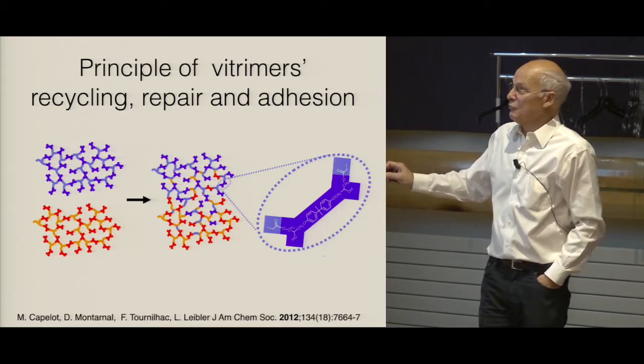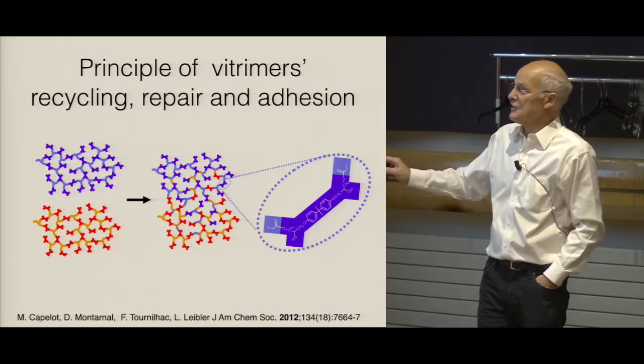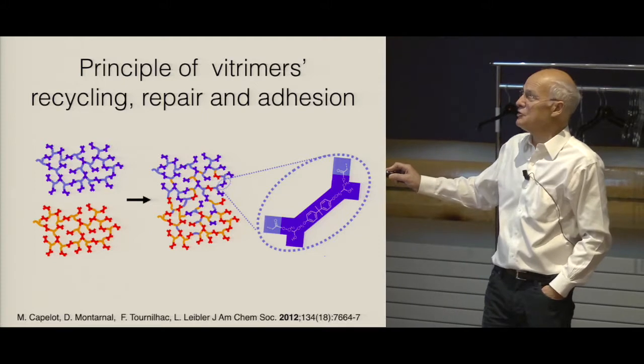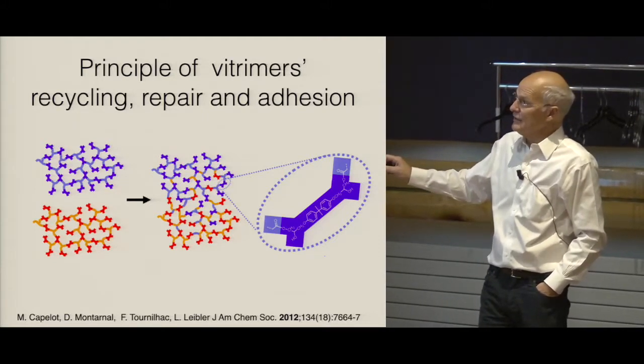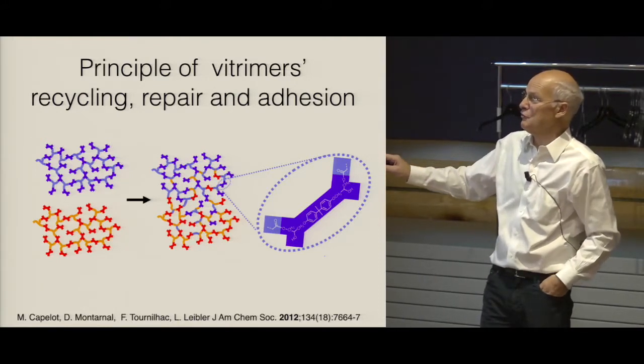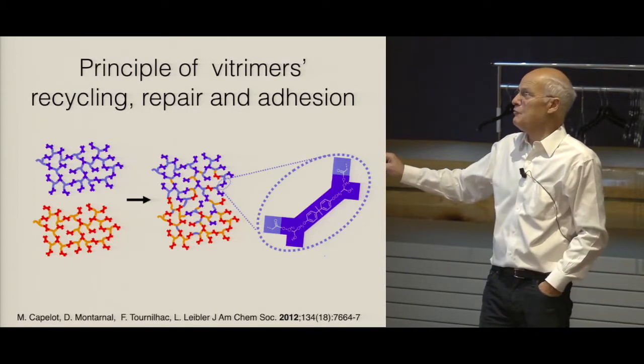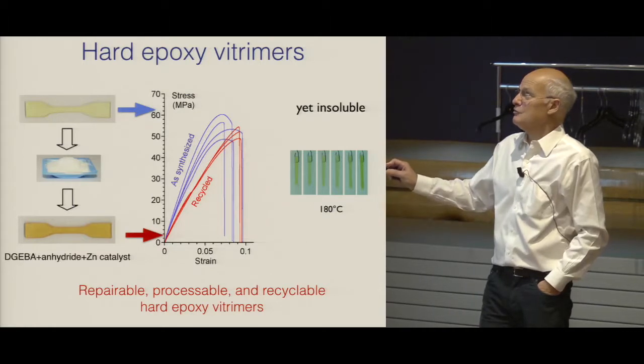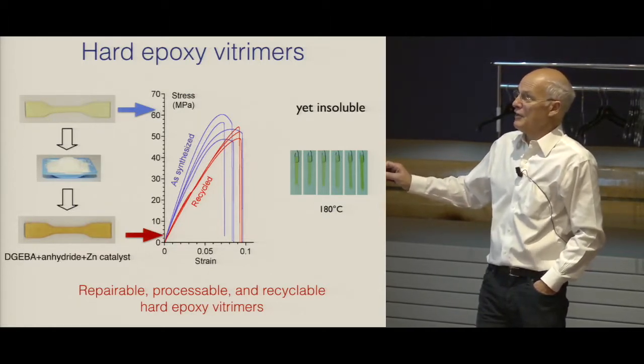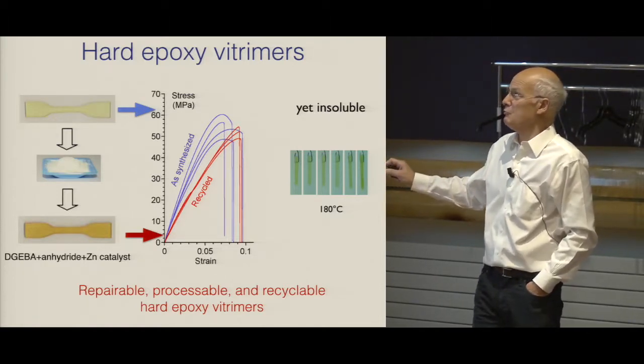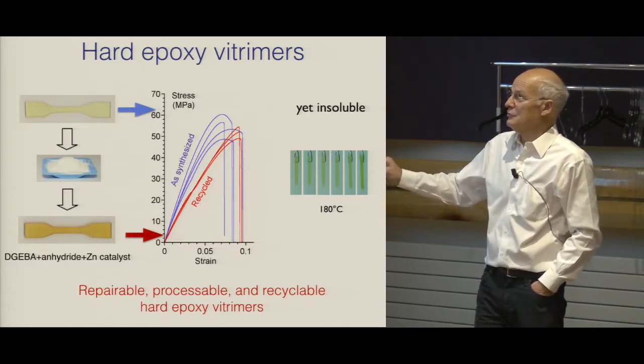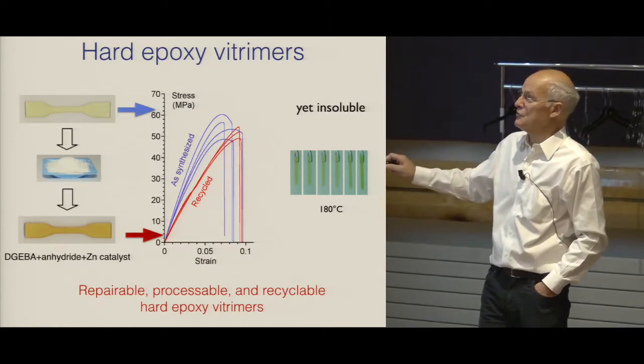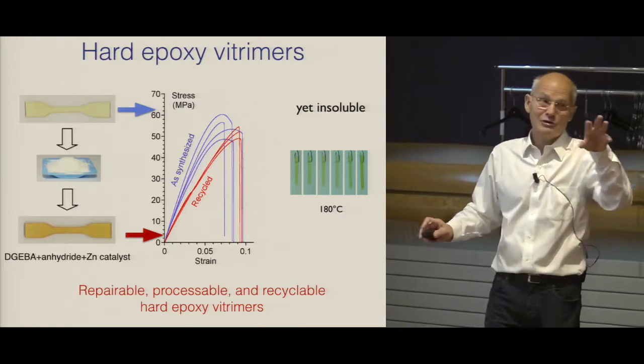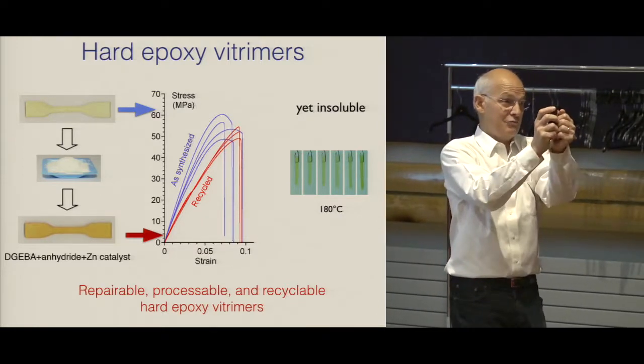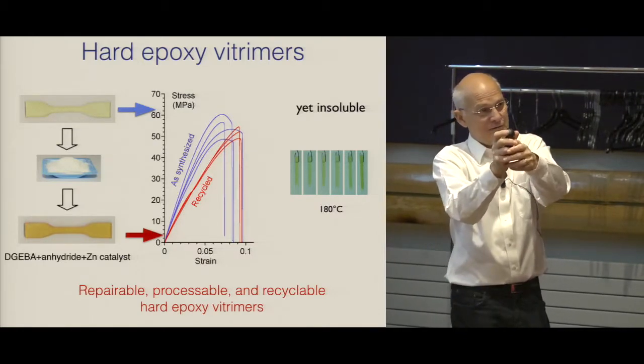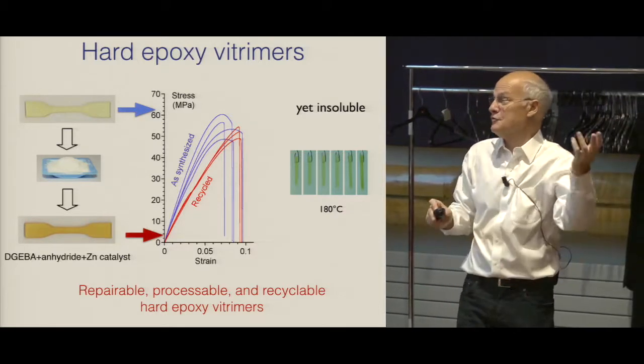We can also repair it and recycle it, because if you take two vitrimers, they have defects at the surface. But if we put them together and we heat them, then we have exchange reactions across the interface, and it becomes just one bulk material because the defects diffuse into the bulk of the material. So you get a perfect adhesion. So this will be a hard epoxy vitrimer. You have a hard plastic, you grind it, it's a cross-linked insoluble plastic, you heat it in a mold, and you get exactly the same, or almost the same properties as you had at the beginning, because with this little powder, you can make adhesion. Okay? So you can recycle and reshape the thermoset, a permanently cross-linked insoluble material.